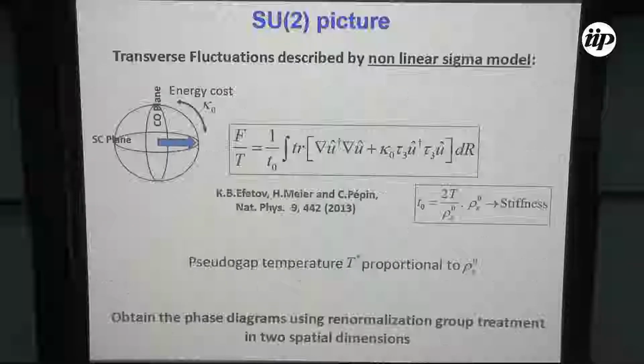In order to study the fluctuations of this pseudo-spin, we started looking at the nonlinear sigma model, where we have this term which is just the difference of the two masses, the anisotropy between the two fields. We have this term which is the gradient of the fields, which will take care of the fluctuations in the problem. So we started doing a renormalization group treatment of this free energy in two spatial dimensions and tried to see what happens to the phase diagram.